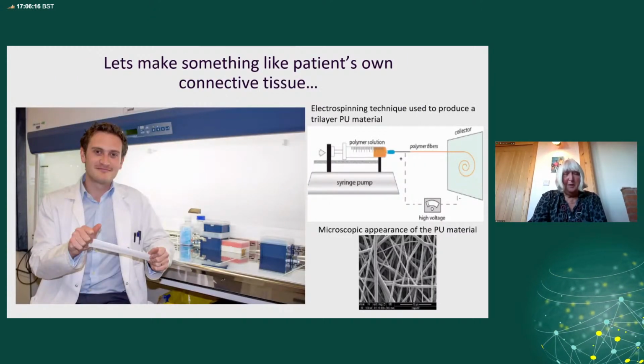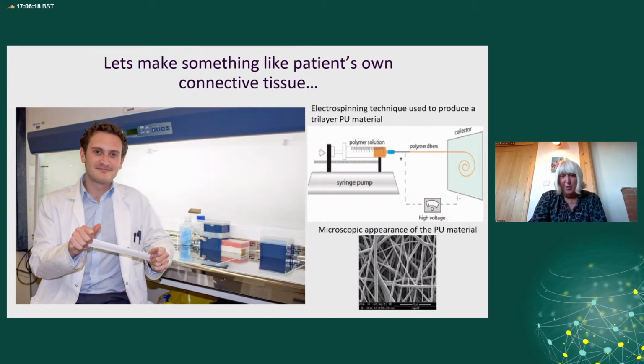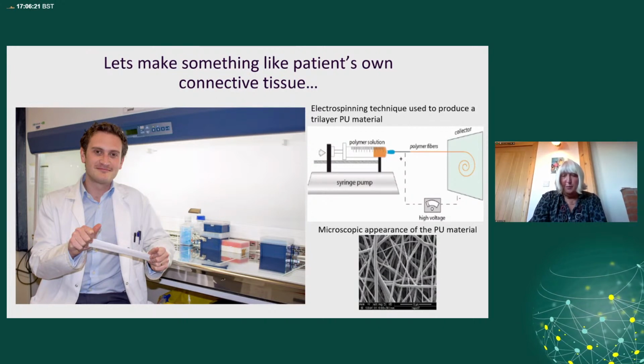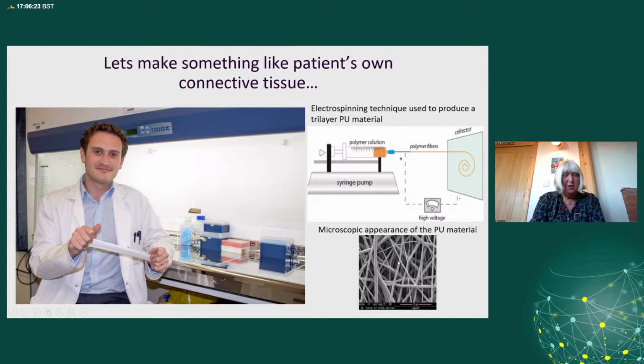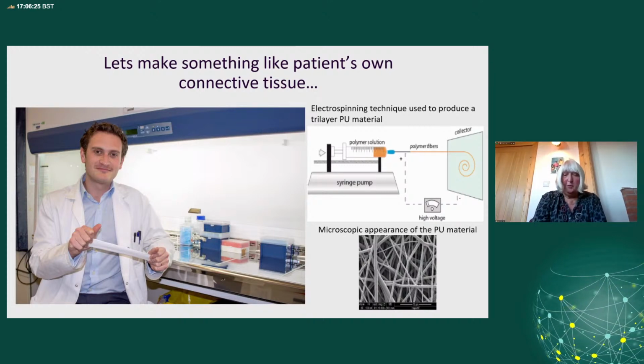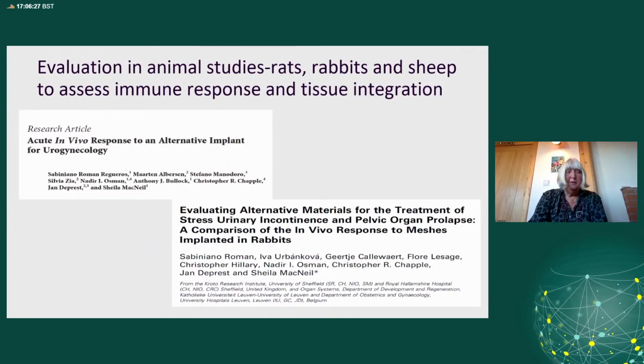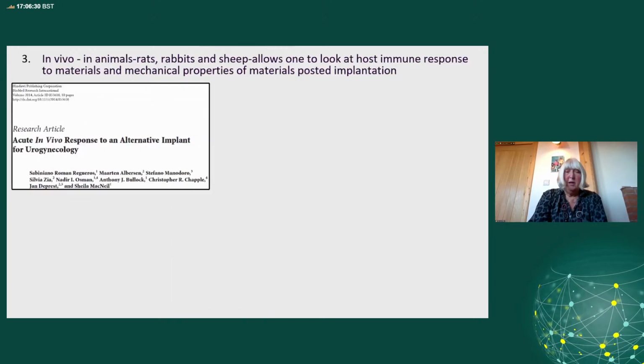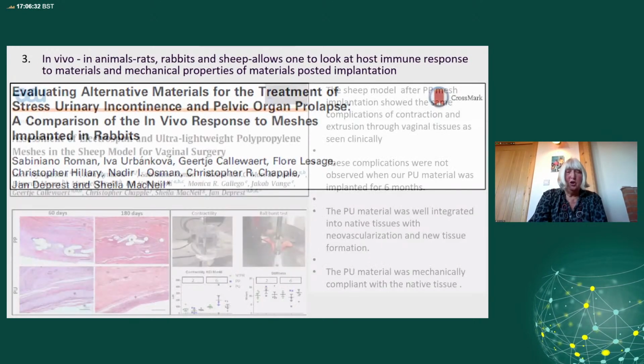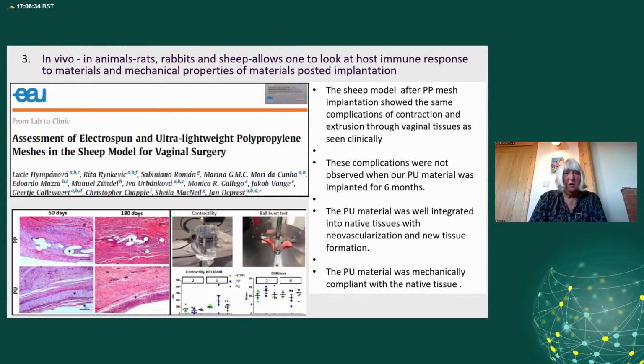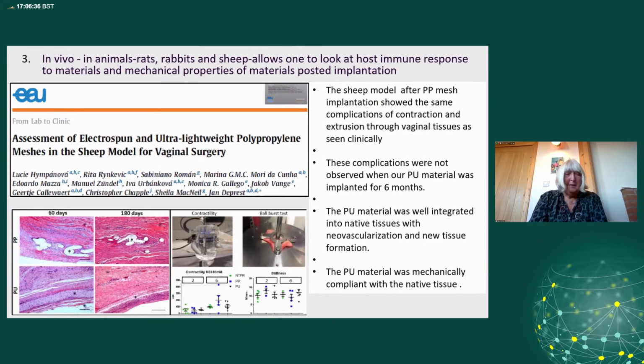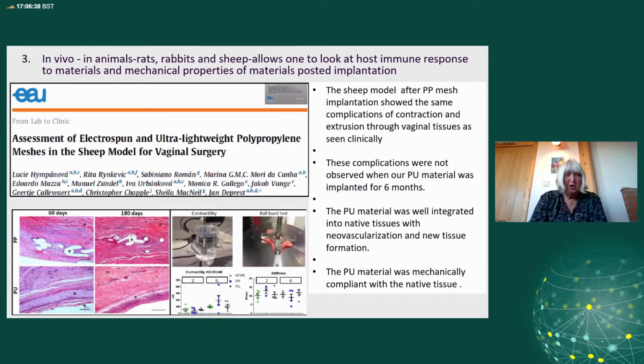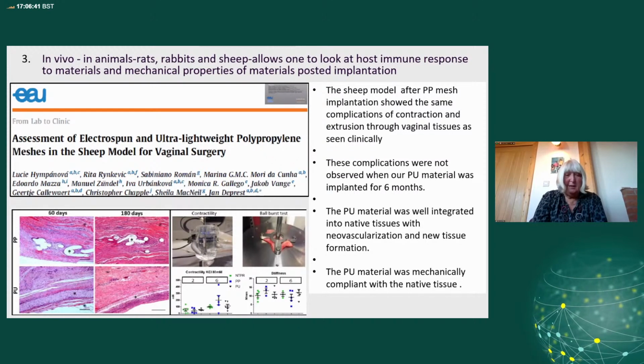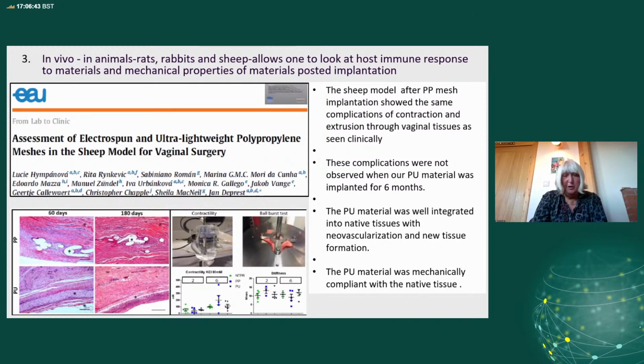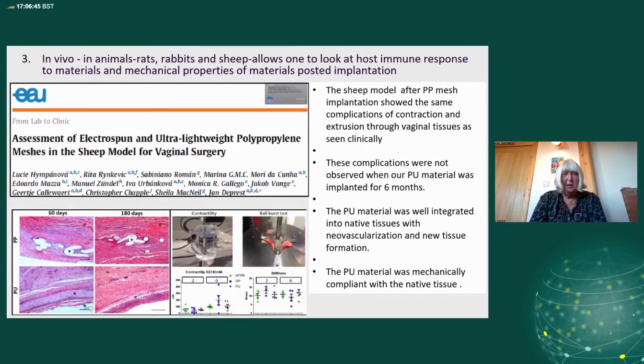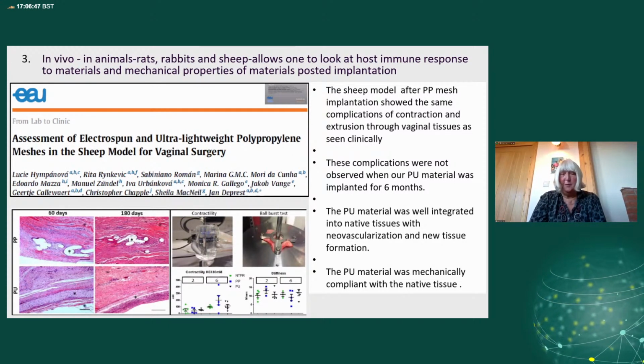So stepping back a bit, here's Chris looking very proud with some of the first electrospun material that we made. And as you can see, you can stretch it and it bounces back. Now, we evaluated this material in rats, in rabbits, and in sheep. And I'm just rattling through these, all published a while ago. Basically, if we implant the material in sheep, then it's well integrated. The mechanical properties of the material are good, and it doesn't adversely affect the mechanical properties of the vagina.